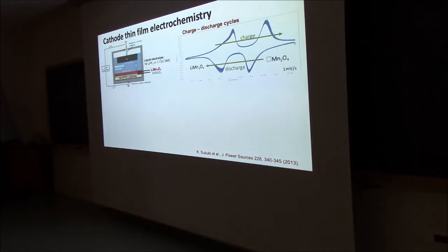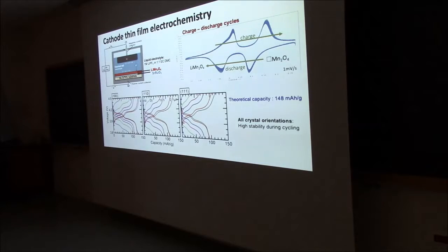So this is not automatically the same. But what I'll show you later, or even here, is that instead of only doing this cyclic voltammetry, you can also look at when you provide a current, what the voltages are doing, so what kind of capacities you are able to get out, and then you can see, are you able to get out the same capacity as what you put in originally? So what's the volume change with the full delithiation?